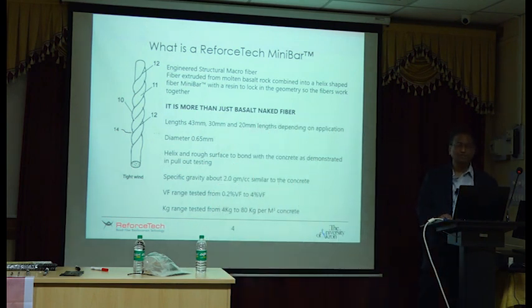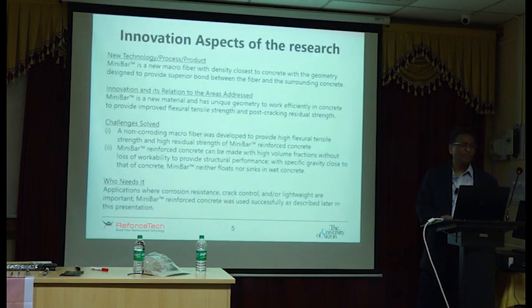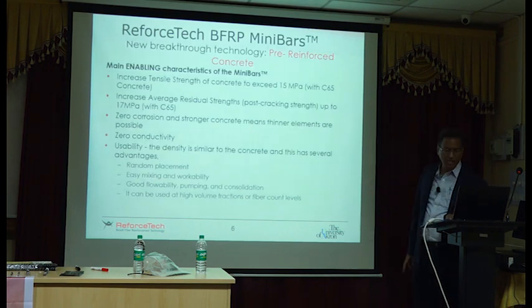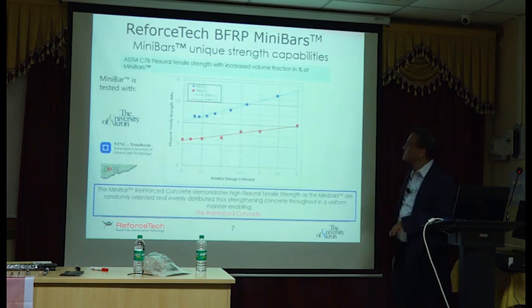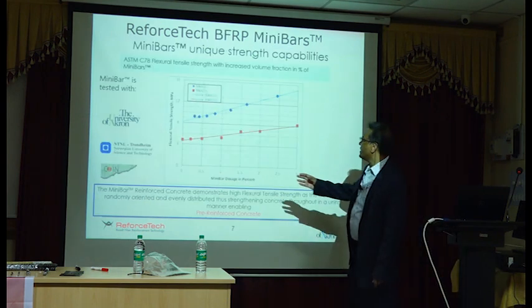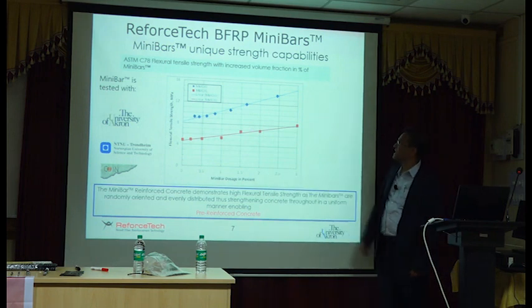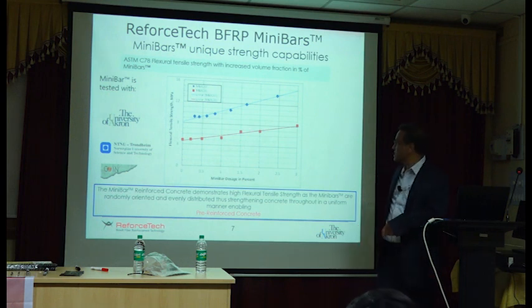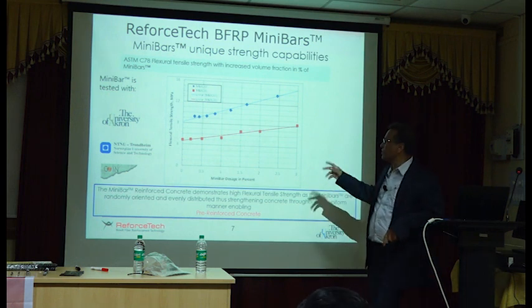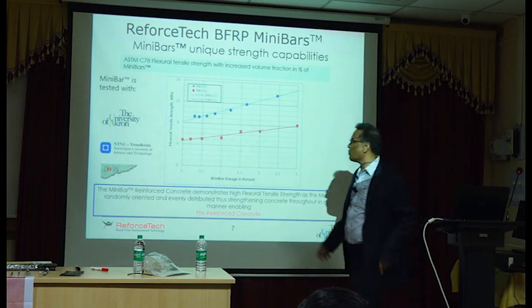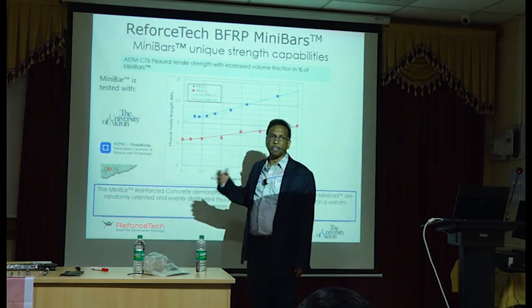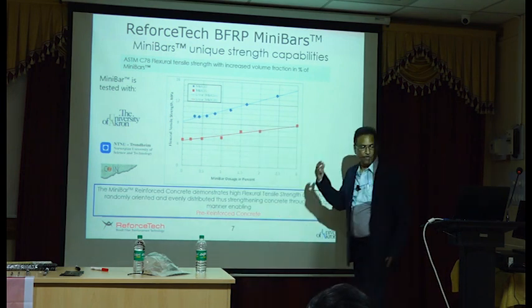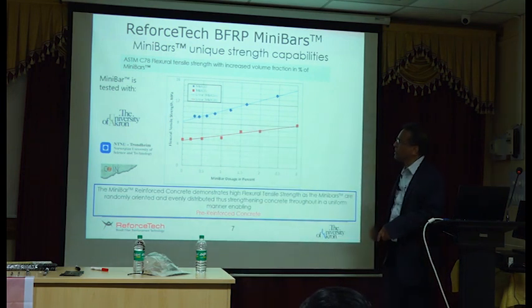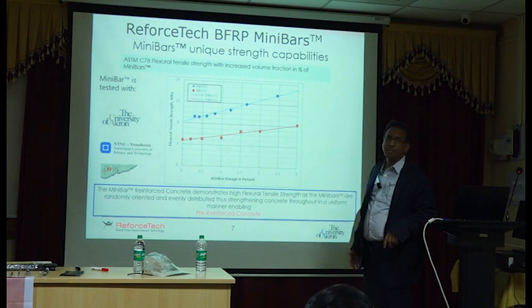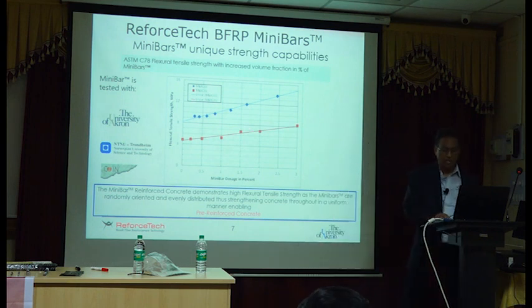Okay, so then we have a few. We'll just move on. We'll not go through every single slide. So we tried dosages as much as 2.5–3%, very, very high dosages. And if you are familiar with polypropylene fiber, if you are using 0.5%, you are very lucky. But with this minibar, we were able to use as much as 2.5–3% of fiber, which is very helpful.